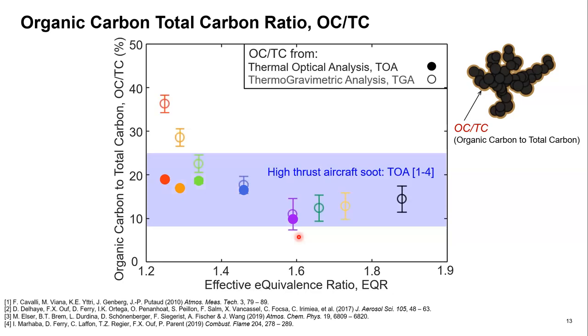We also estimated the OC/TC ratio from thermal gravimetric analysis, where we measure carefully the mass while we ramp up the temperature under nitrogen and then under an oxidizing environment. And what we see here is that at the smallest equivalence ratios, we have a slightly higher OC/TC ratio. And this begins to decrease, coming into agreement with the thermal optical analysis at equivalence ratios of 1.46 and 1.59. And at the much richer conditions, this starts to increase slightly again.